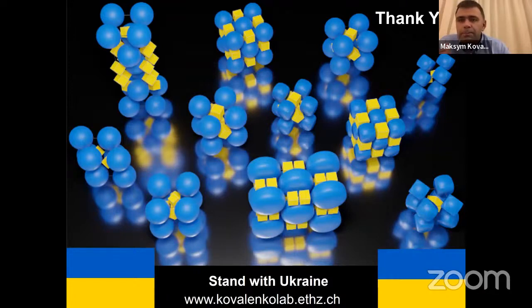Perovskite doped glasses. Another question is from Aytac about the perovskite doped glasses. Very good question. In literature, you're right, there is an increasing number of works where people produce perovskite quantum dots by melting the precursors together with the precursors for the glass. And then when they anneal it, they produce perovskites in the glass, similar to one of the actually very first examples of quantum dots in the history 40 years ago. So this is indeed a very good idea.